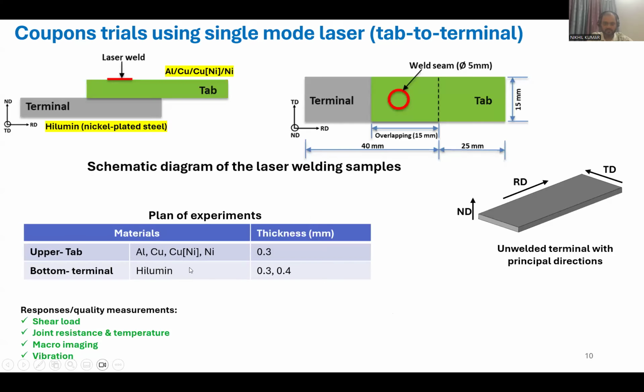After welding, you can consider this schematic as one of the weld pieces. This is a schematic diagram of one of the weld pieces. You can consider the weld is going to be formed like this. You will have a terminal on the bottom side and a tab on the top side, and you have a weld with a circle shape, a 5 millimeter diameter weld seam. After welding, I am going to measure the lap shear load, joint resistance, temperature, and macro imaging. I would say the weld cross-section analysis, because this is very important to capture the weld depth.